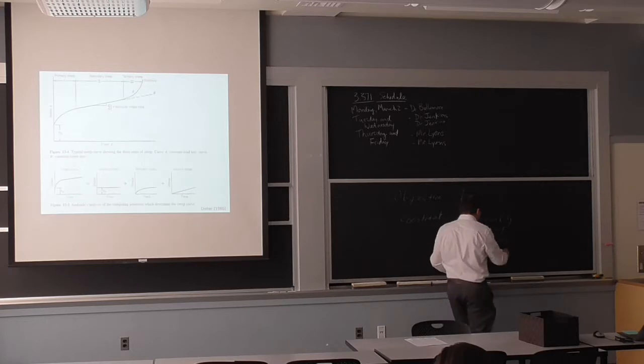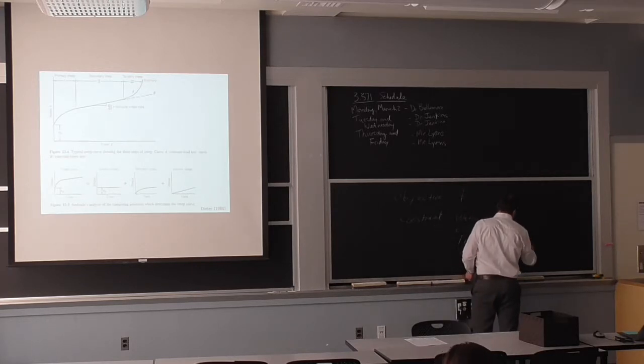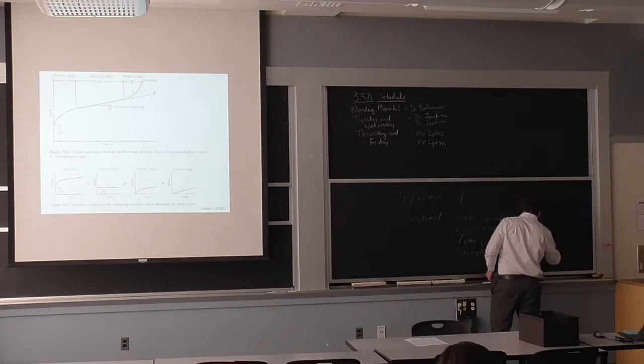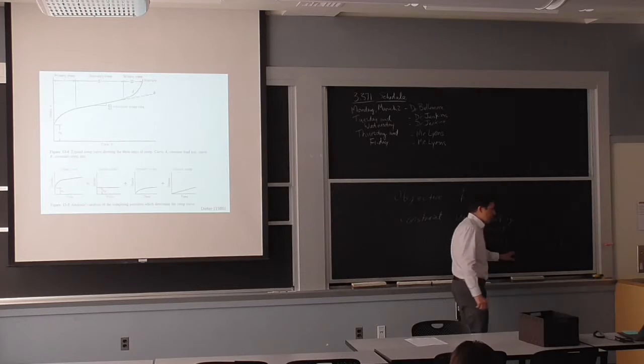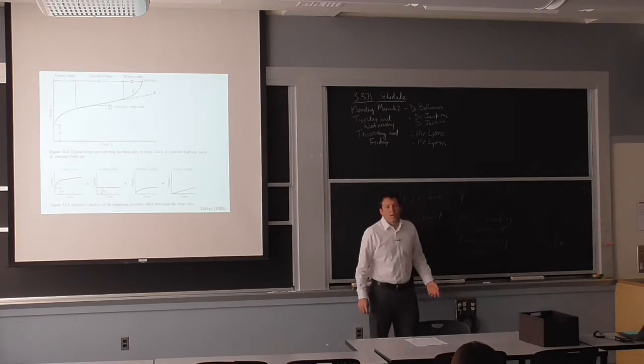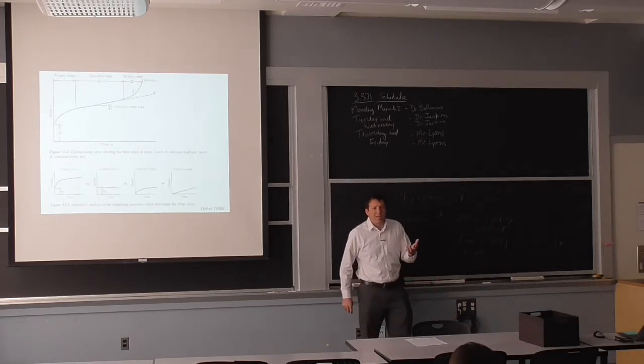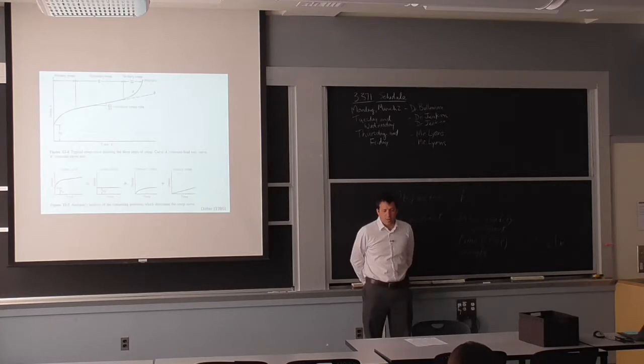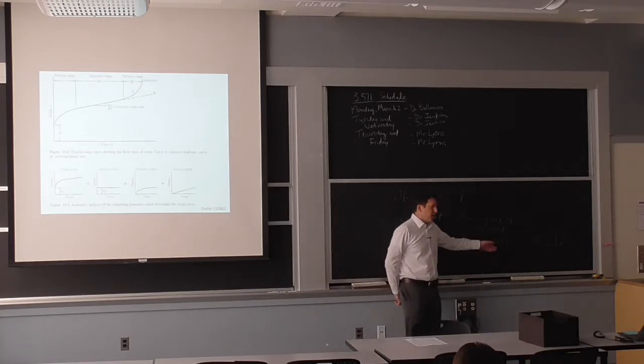What I could say for creep here is if the temperature is greater than about half of the melting temperature, is when you can expect having some creep effects. So for lead that we discussed a little bit on Monday, and tin, that could be very close to ambient temperature because of a low melting point. But for steel or even aluminum, you have to elevate the temperature before any of this takes place.